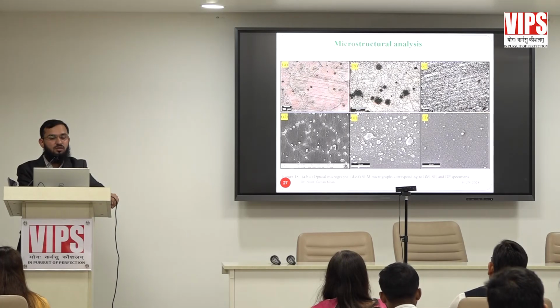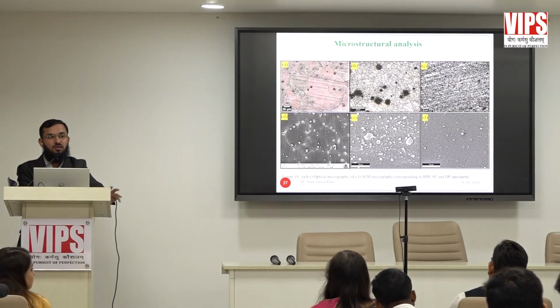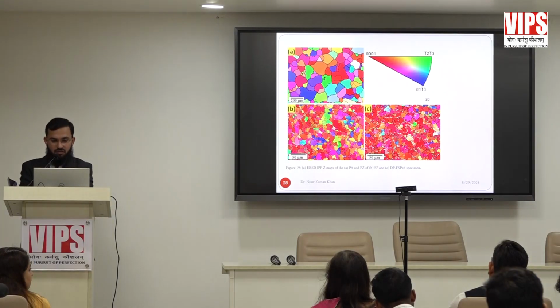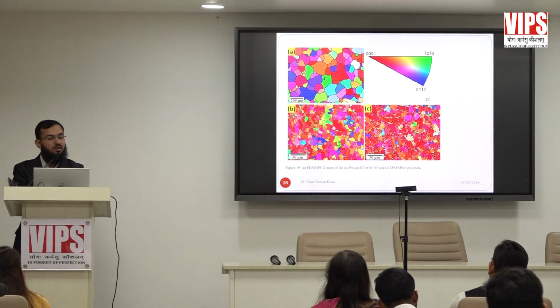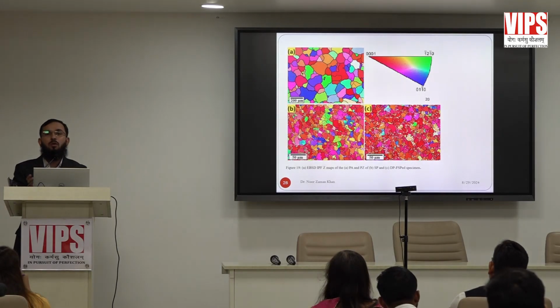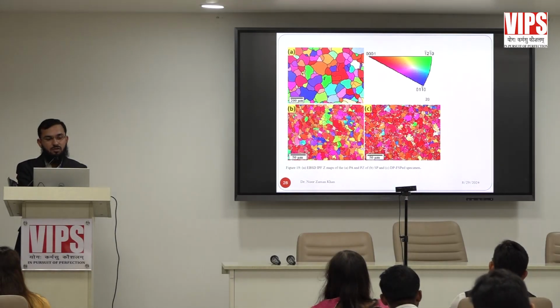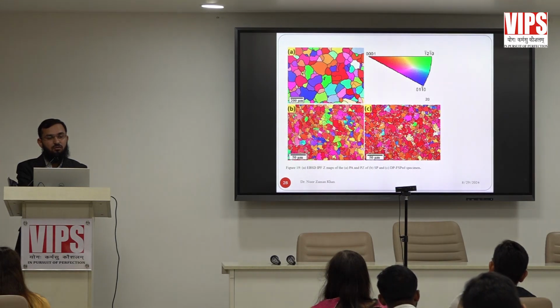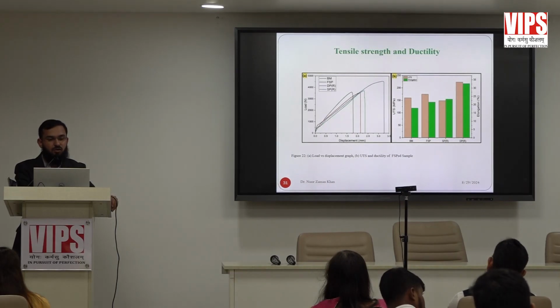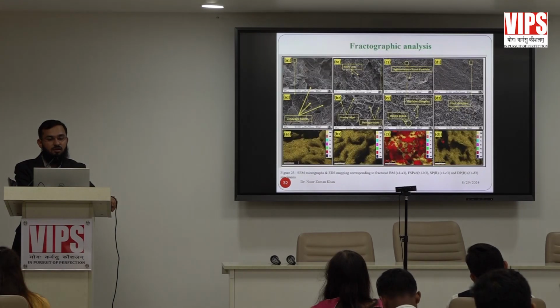If you see the microstructure, figure A is the base material microstructure, and B and C are the friction stir processed microstructure. You can see the difference in the grain size. A is the base material, the raw material, and B and C are the material after friction stir processing, or you can say after severe plastic deformation. The drastic reduction in the grain size means we can enhance the strength. Micro hardness, tensile strength: you can see the base material tensile strength, and you can see the processed tensile strength.